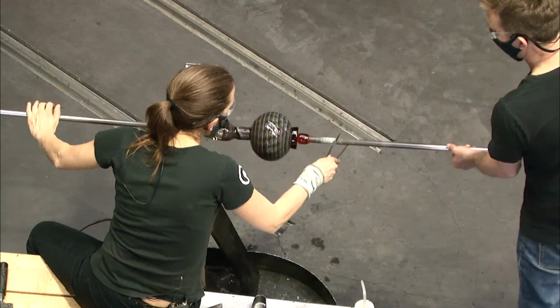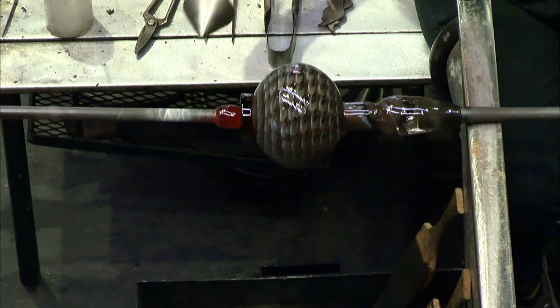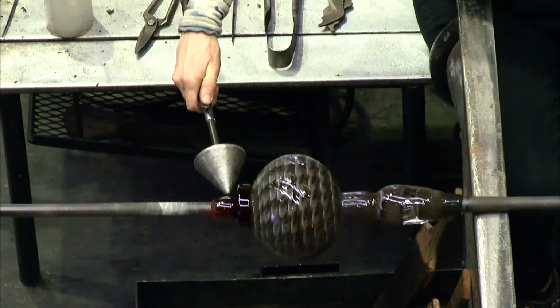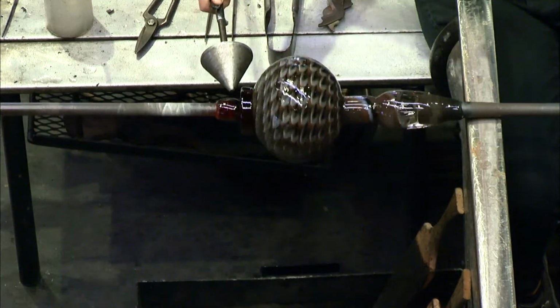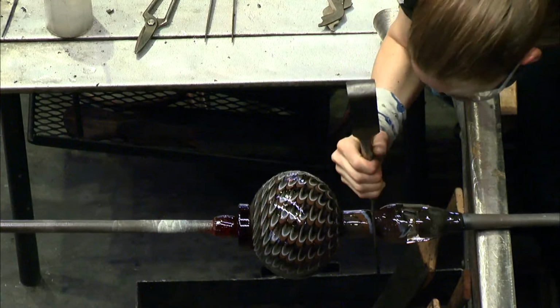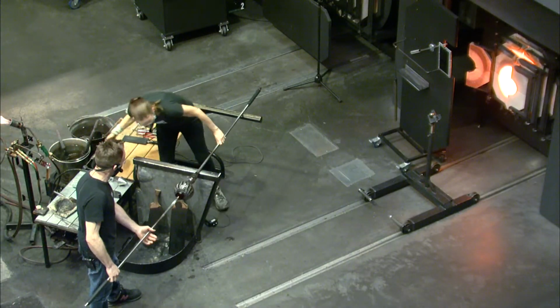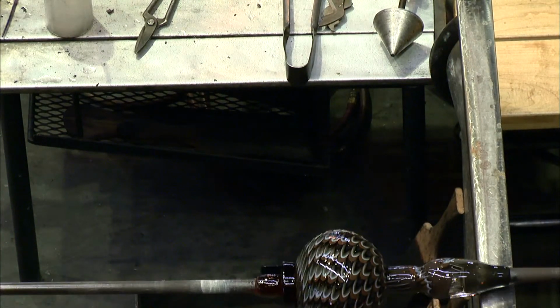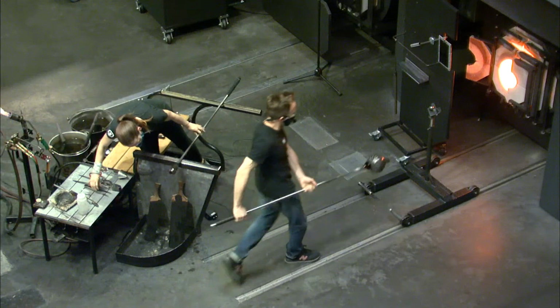Helen has timed this as well so that her bottle is in its rigid state. We call that cold glass, and that just means 1,000 degrees. That's where this soda lime glass is rock solid, though. A quick little shock with that metal tool on that line, and she'll put a little bit of water on there. Let's get a little tap. This creates tiny stress cracks and a little vibration to do the rest. Nice job.